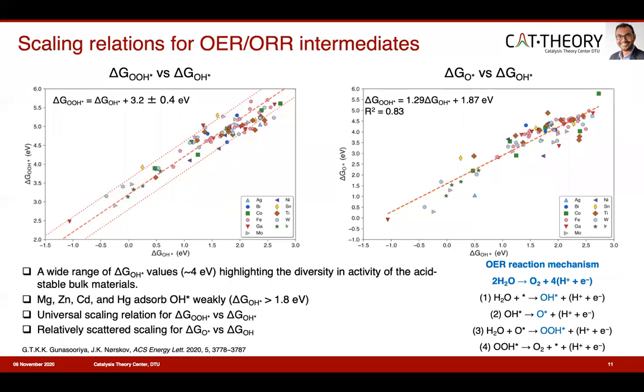Now let's look at the scaling relationships. As shown in reactions 1 to 4, the associative OER reaction mechanism involves OOH, OH, and O as reaction intermediates. And it is well established that OER reaction intermediates follow linear scaling relations, since all the intermediates adsorb to the surface active site through an oxygen atom. At first glance, a wide range of ΔG_OH values are observed. You can see it's ranging over 4 electron volts. And this highlights the diversity in activity of the acid-stable oxides. As expected, some elements bind oxygen intermediates weakly, and we see this universal scaling for OOH versus OH. However, the OH versus O scaling is rather scattered.